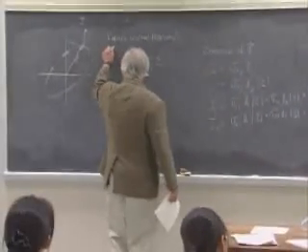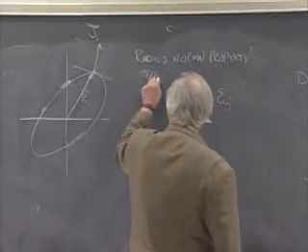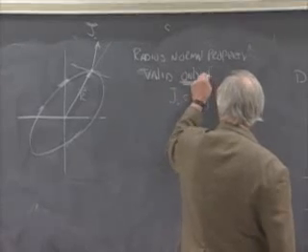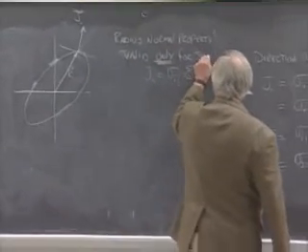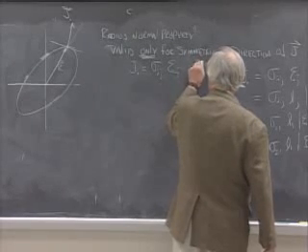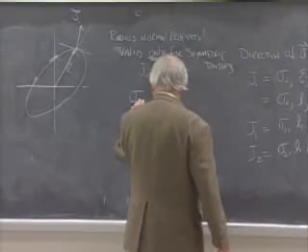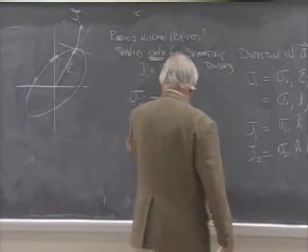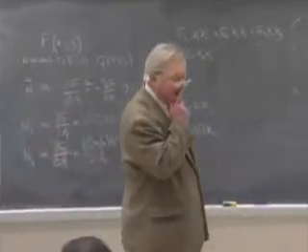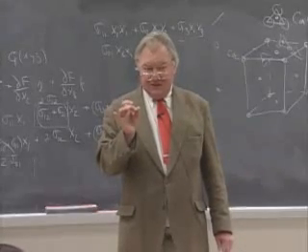So the radius normal property will be true or valid only for symmetric tensors. That is, it's going to be true only if sigma ij is equal to sigma ji. And we mentioned when we first started talking about second-rank tensors that a tensor does not have to be symmetric.